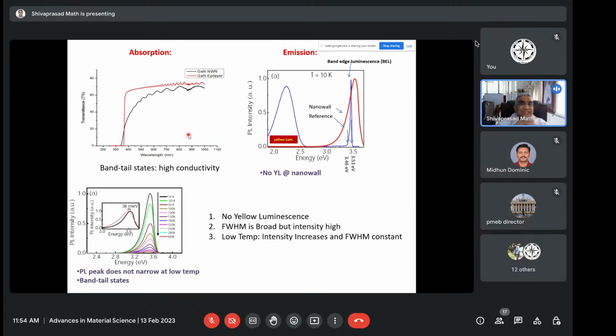But what was very interesting about these materials is one of my students just touched with the multimeter and he found this material very, very highly conducting, which is surprising. With a band gap of 3.4 electron volts showing photoluminescence of that value, it should not become conducting because there are no free electrons in these materials. So how are they conducting? Then it gives us a new dimension for this study. And we started studying why are these so well conducting.